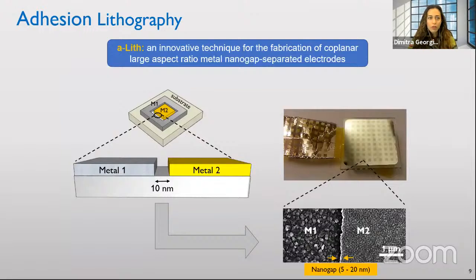So today I will introduce to you a novel technique. It's called adhesion lithography, and it's an innovative fabrication technique to get coplanar, large aspect ratio, metal nanogap separated electrodes. As you see here, we have these coplanar electrodes. They can be the same or different metal, and they are usually separated by a nanogap of about 10 to 15 nanometers. Also, you can see that on this substrate, for example, in one fabrication step, we can deposit plenty of devices on the same substrate.